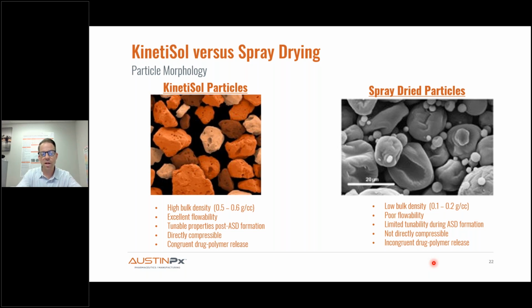So incongruent drug polymer release, if you go back to that figure that I showed earlier, that means the drug is out in solution, potentially naked, without polymer protection, and you get nucleation and crystal growth. Whereas with congruent drug polymer release, you don't. So KinetiSol dense particles, like the ones you produce with KinetiSol and melt extrusion, promote congruent drug polymer release and maximize the fraction available for absorption, whereas high surface area particles do not.